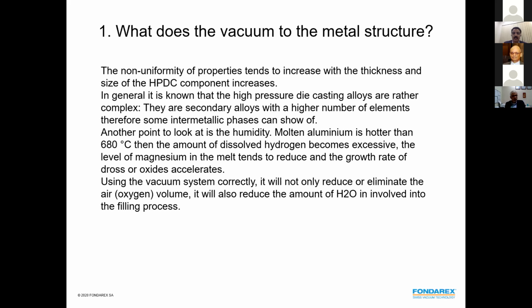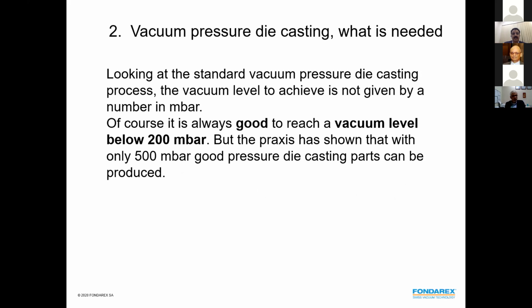The hydrogen, of course, mainly comes up in pressure die casting because most die releases are water-based, and therefore we have a little bit more H2O, which is getting mixed with the alloy structure. And there we come also to a positive point with the vacuum, before we even talk about the level, because the vacuum basically also takes out part of the humidity. This is happening already below 500 millibars. And of course, for a good application, we'd like to get 200 millibars or even below in high quality pressure die casting with vacuum.